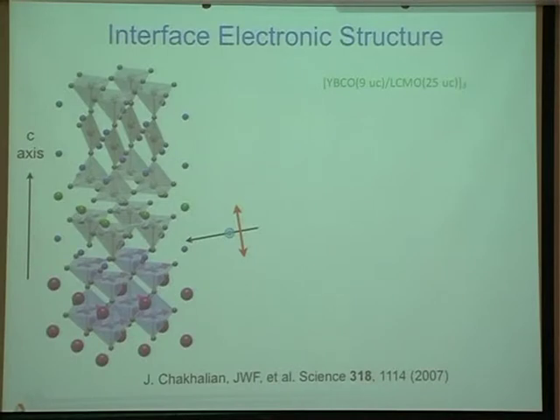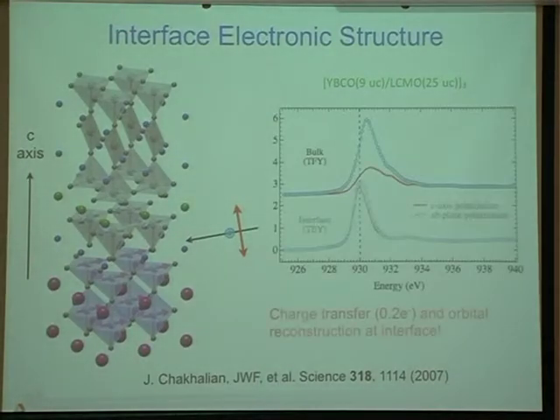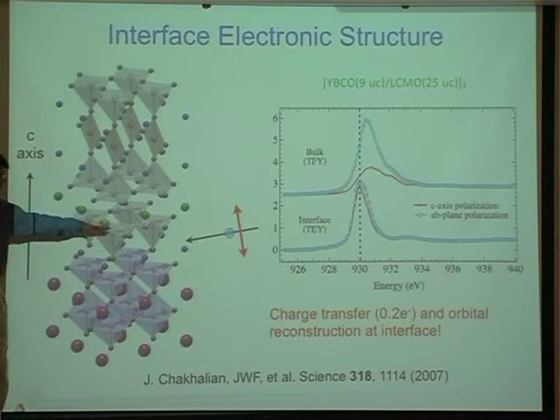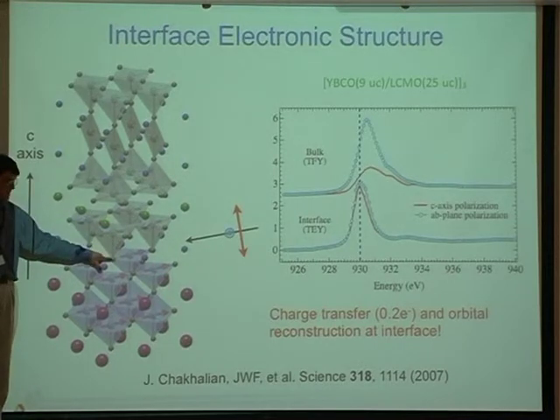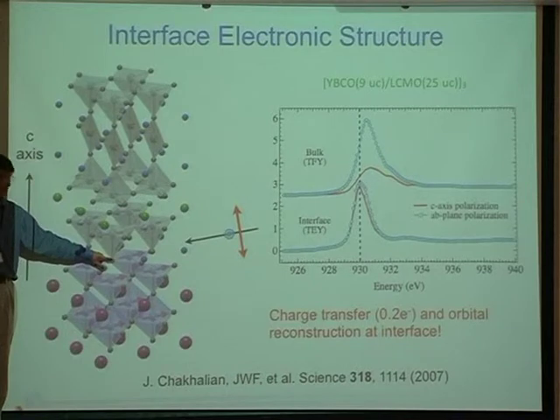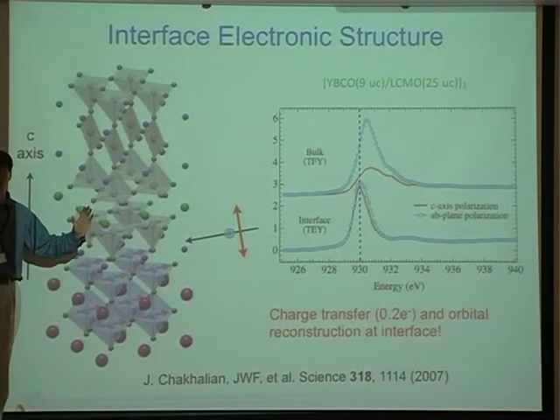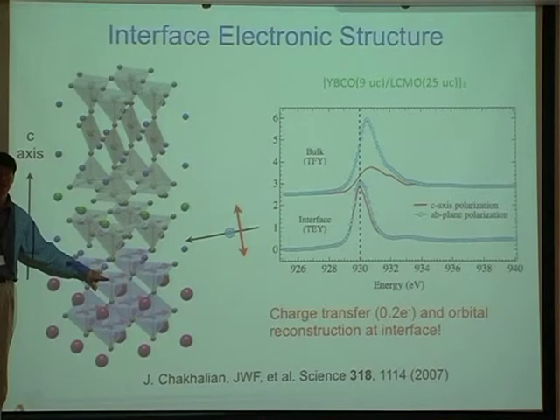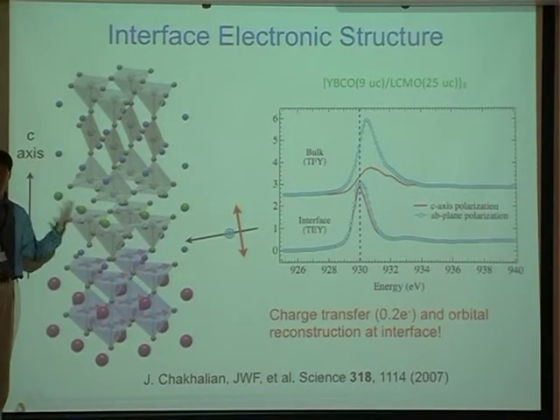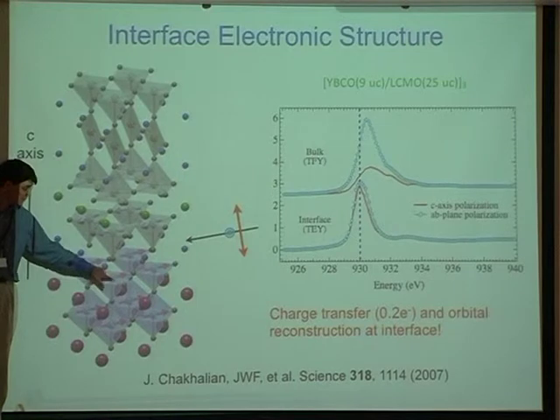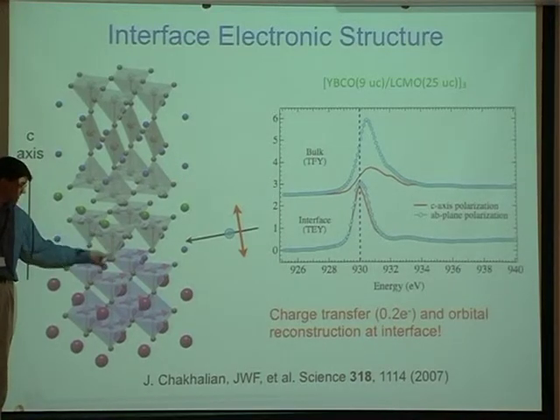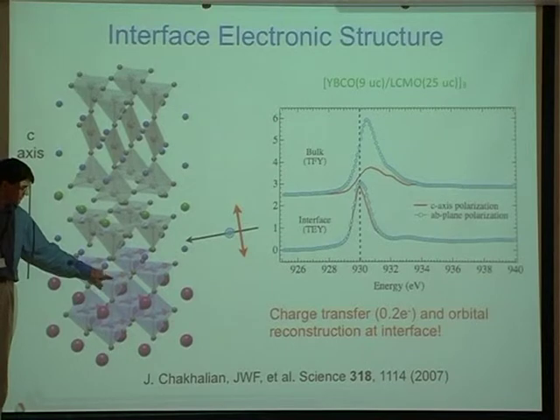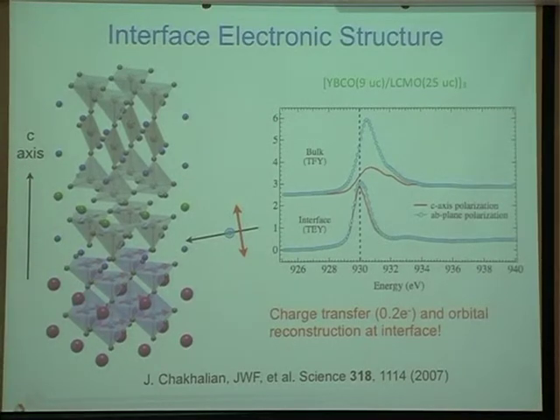And actually, I don't know if I have the picture. The simple model was the following: I have a copper-oxygen plane, it's coupled to this apical oxygen. Now, normally in the cuprate, this apical oxygen is connected to nothing else. But now I've connected it to a manganese. So I basically made it a three-dimensional entity. And depending on what's going on in this manganese, I can hybridize with this copper. And depending on the details of where the D states align in the two layers, you can cause a kind of state where you mix up the two orbitals.